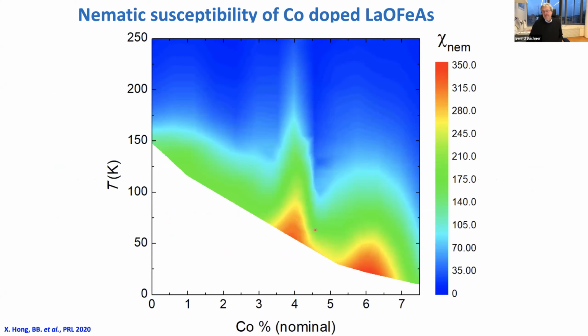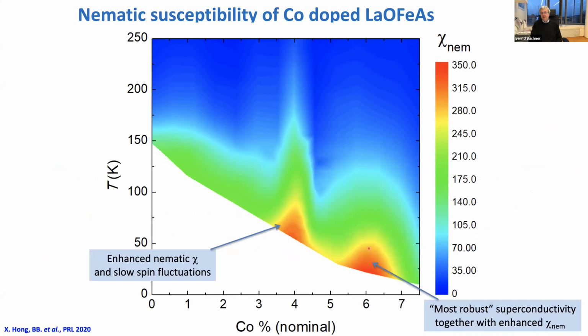And then you see what I would call a double dome feature for this nematic susceptibility. Of course, this is mimicking our superconducting dome. Just taking the strain derivative of the resistivity, we can directly see the region where superconductivity occurs, with a maximum at about 6%. The other special point in the phase diagram is close to the region where magnetism disappears. It's natural to assume that this is the coupling between nematic fluctuations and spin susceptibility.